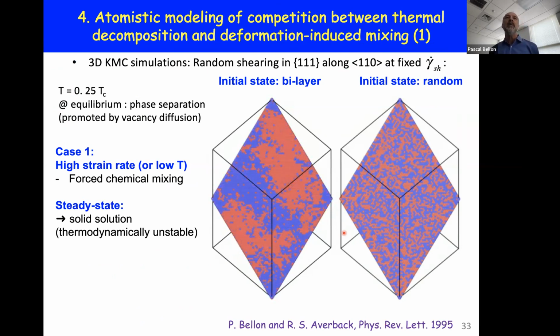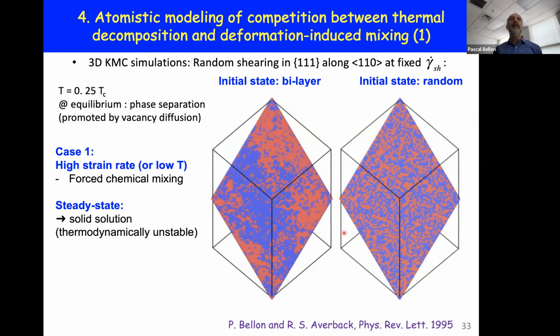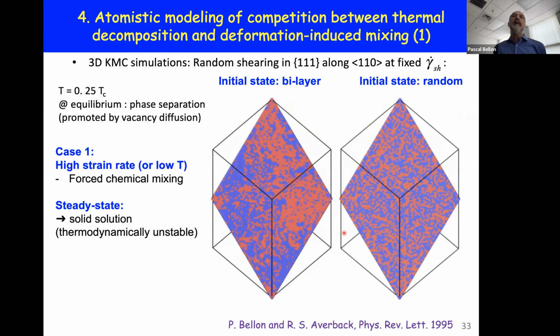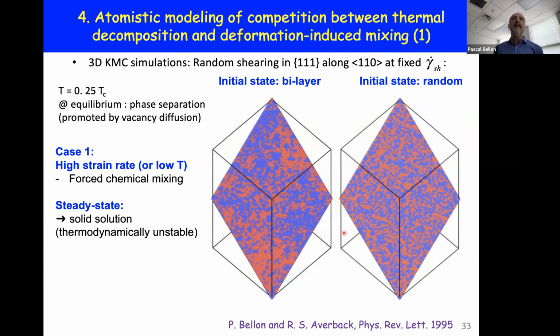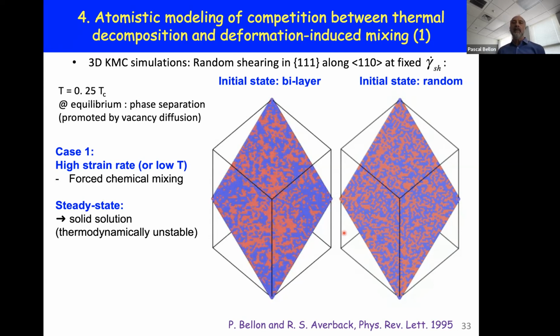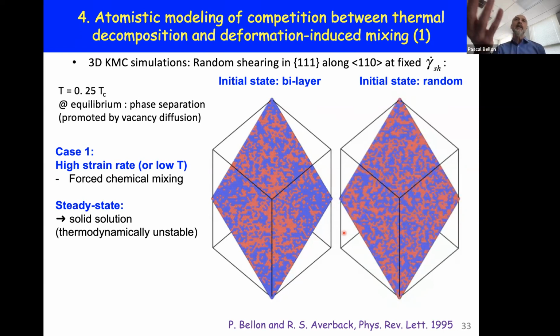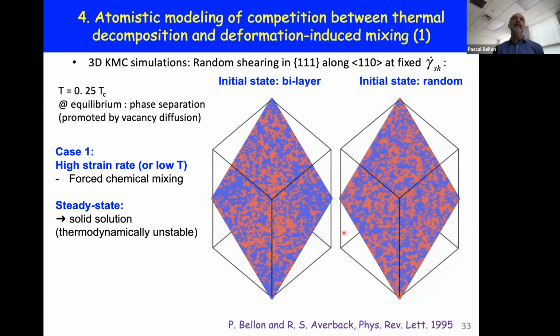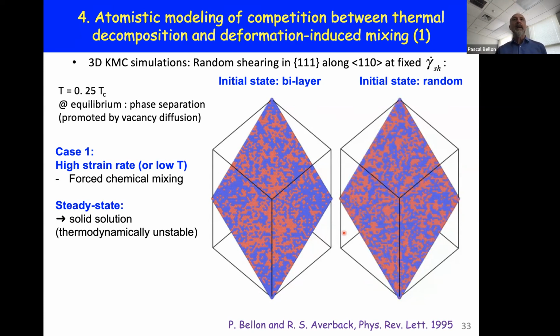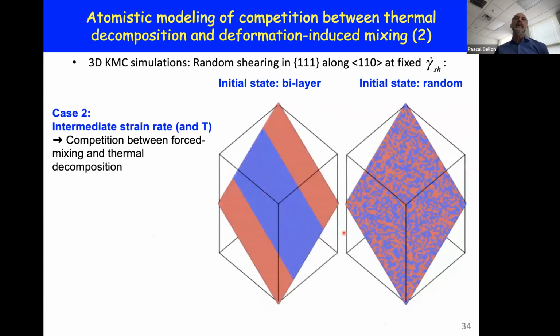On the left-hand side, this was a bilayer structure in an FCC lattice that we model using kinetic Monte Carlo simulations. You can see that the A and B atoms, red and blue, started with a bilayer, but after a while they formed a solid solution. And if we start with a solid solution, we get the same steady state. So this is the case of either irradiation or severe plastic deformation at low temperature. What's more interesting is when we do that at intermediate temperature. If we start from a bilayer, you see that first there is kinetic roughening at interfaces, and then progressively we form protrusions. These protrusions may detach from the original layers, refining the microstructure. And this microstructure is progressively refined.